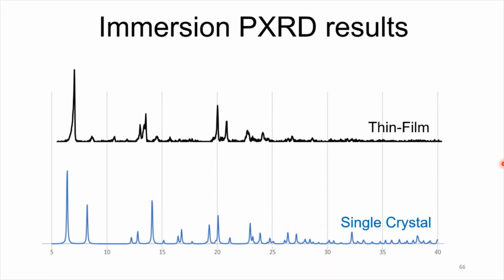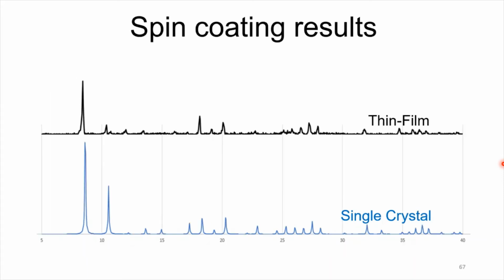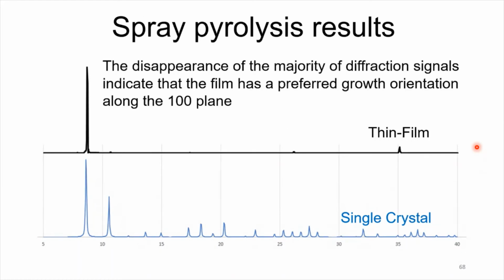thin layer of crystals. Now, spin coating, that actually started giving us better results. As you can see, the intensities from these two peaks, this one is more decreased than what we hope to see. So there is definitely some growth that we are hoping we're getting. But what gave us the best results so far is the spray pyrolysis result.